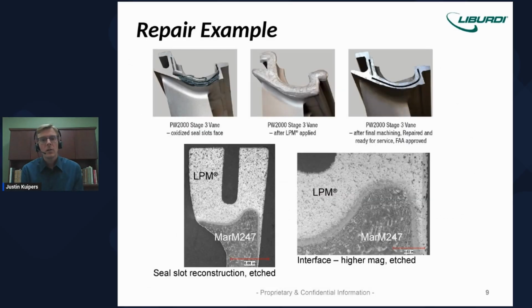We're going to move on now to some examples of repairs that we do with our LPM process, starting with repair of the PW2000 stage 3 vane. This is an FAA approved repair that we do. The parts experience hot corrosion damage during service, which you see at top left in the seal slots on the sides of the components. We go in and mechanically remove all of that corrosion scale and damaged material and end up with a widened slot or groove.